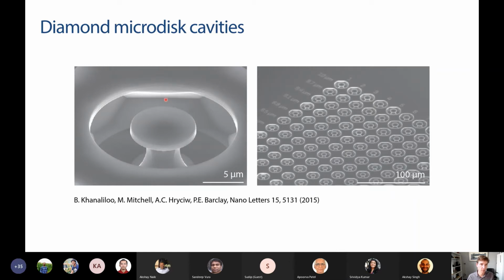And these sharp angles that you're seeing are actually crystal planes of the diamond that are being etched in a very chemical manner by our fabrication approach. And I should mention that the tools that we use for fabricating these are nice clean room tools, but they're nothing special. Basically they're standard Oxford plasma etching tools that you would find in most clean rooms in the world. They're not new. They've been around for decades.